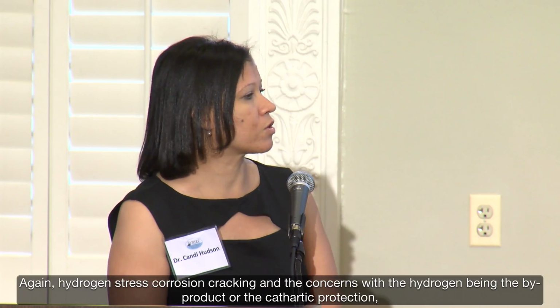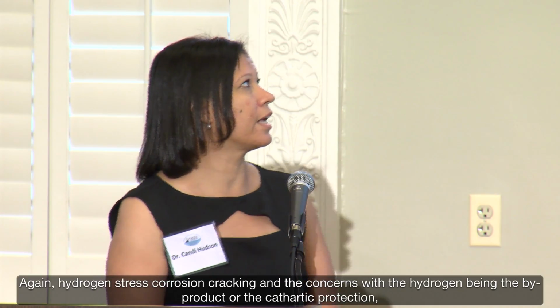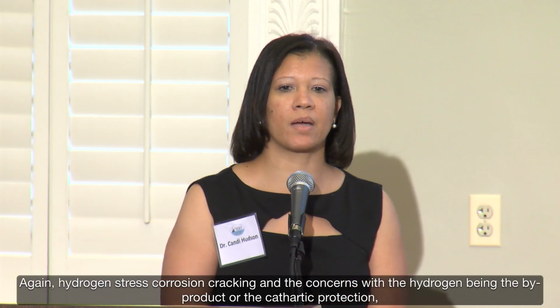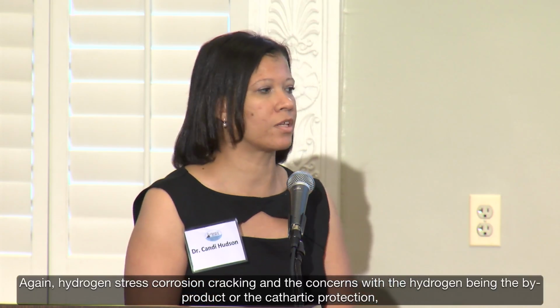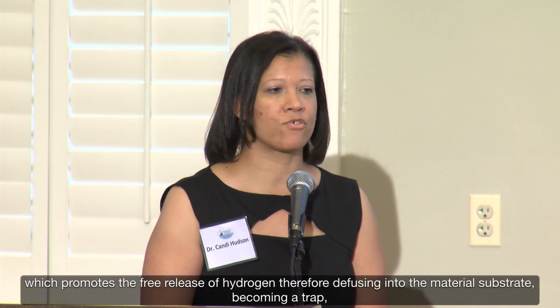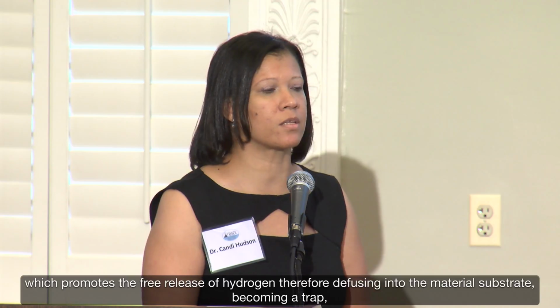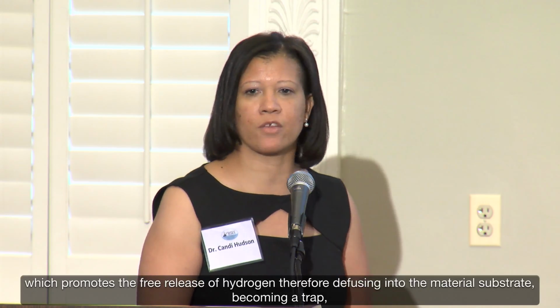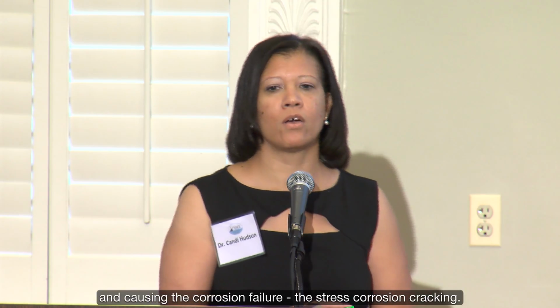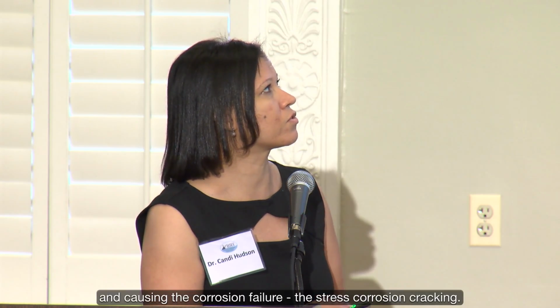Again, hydrogen stress corrosion cracking, and the concern with hydrogen being the byproduct of the cathodic protection, which promotes the free release of hydrogen, therefore diffusing into the material substrate, becoming a trap, and causing the corrosion failure, the stress corrosion cracking.